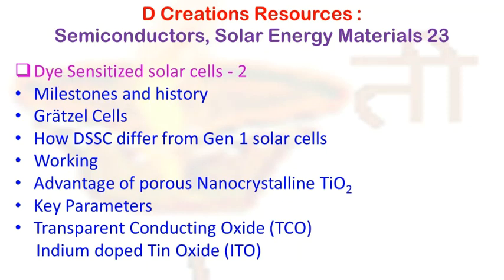The earlier photochemical studies of dye sensitization of semiconductors focused on flat electrodes, but these systems were facing an intrinsic problem. Only the first monolayer of adsorbed dye results in effective electron injection into the semiconductor. But such light harvesting from a single dye monolayer is extremely small. By application of nanoporous TiO2, the effective surface area can be enhanced 1000-fold. That's why TiO2 is important in dye-sensitized solar cells. In fact, a solar cell based on a dye-sensitized porous nanocrystalline TiO2 photoanode, which performed very well, was first reported by Grätzel. So this was about the importance of TiO2.